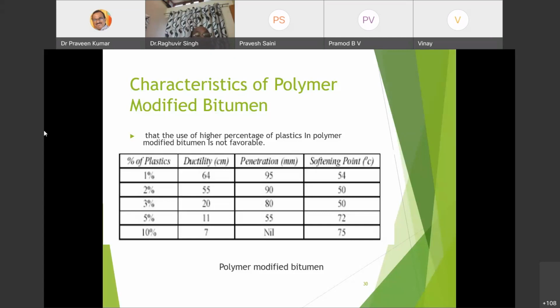As the percentage of plastic increases up to 5%, ductility reduces to 11, penetration 55, and softening point 72. With plastic increased up to 10%, ductility reduces to 7, penetration is nil, and the softening point increases to 75.